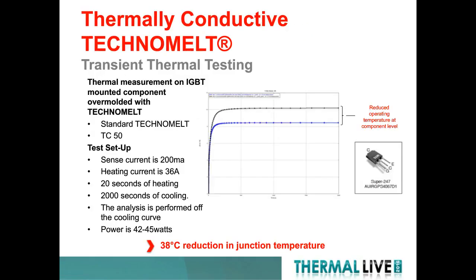How does this look in a more realistic setting? We took this IGBT, which you can see in the image on the right, and mounted that to a circuit board. After mounting to a circuit board, we then molded these parts. So we put them in a low-pressure molding tool in a mold set, injected the standard Technomelt around that tool set, and encapsulated the part, leaving just the pins themselves exposed.